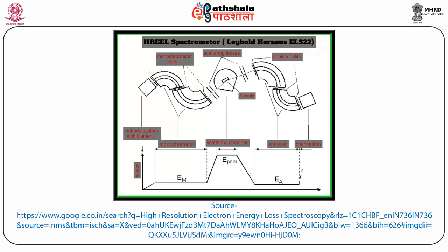Schematic diagram of this. The spectrometer used here is labeled HREELS ELS22 model with two 127 degree deflectors. The drawing shows the setup, and a diagram of the kinetic energy of the electrons in the different parts of the spectrometer is shown. The energy in the scattering chamber, E primary, can be varied from a few electron volts to several hundred electron volts. Higher energies are required for the measurement of excitation with a momentum parallel to the surface.